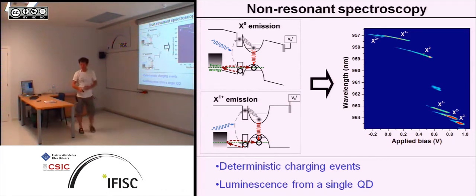No, you have millions in the wafer, but you grow them with a density profile, so the density goes from high to very low, and then you just pick the region where the density is very low, and then you can move the sample around, and you see a region. I mean, maybe, this is from 957 nanometers to 964, so maybe there's another one all the way up here, but you can isolate them spectrally. But you can also make the density so low that you only find one. So, yes, but all I'm showing is single quantum dot spectroscopy. Where was I? Yeah, the record charging shown so far, I think, was from +7 to -8 or something. So it's really a very versatile structure.